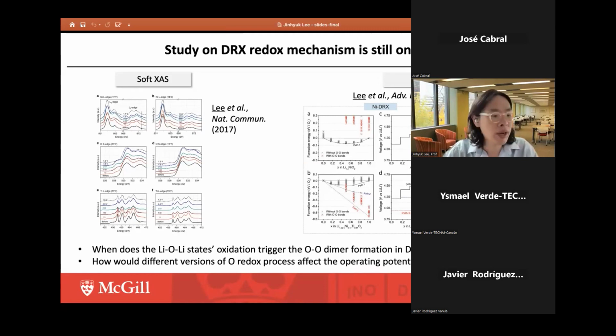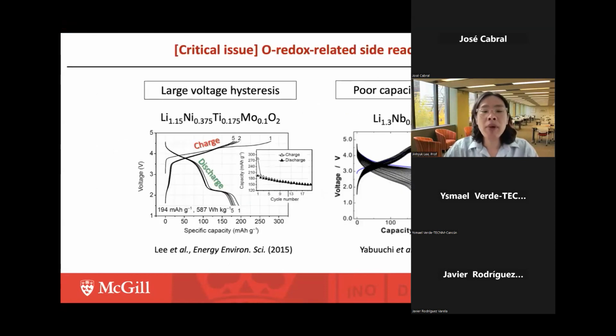Now, so far I've been talking about lithium diffusion, which is possible with the lithium-excess composition. But at the same time, I discussed that because of the lithium excess, we now have to rely on both the transition metal and the oxygen redox process. And what we found is that because of this, we enter into some critical issues related to oxygen redox related side reactions.